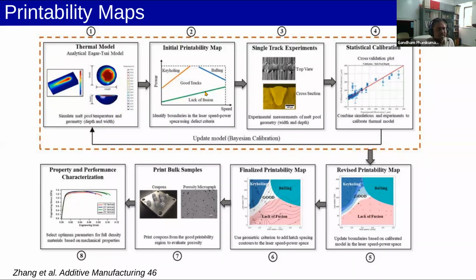And once you have got that, then you can use a single track to do those calibrations and ensure that these lines are available. And there must be some statistically meaningful calibration, because these powder distributions always have slight width. So if you have 30 micron powder, that doesn't mean everything is 30 micron. You know that it's a range of, let us say, 20 to 40 micron, for example.